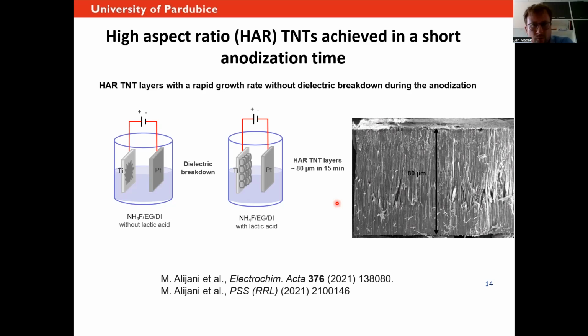Again, the pioneering work on that was shown by the Schmuki group, but we have taken this and made a much deeper investigation, and we have tried to use also different concentrations of the lactic acid. And the beauty about it is that the lactic acid prevents the electric breakdown, which normally occurs when you apply too high voltage. So to make it very clear for you, for instance, if you apply 100 volts, most likely this will be too much.